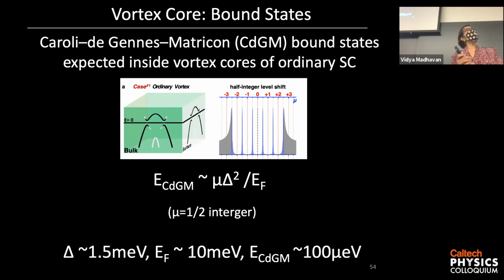So the question is, how do you distinguish these trivial bound states from Majorana bound states? And the first thing is that these trivial bound states are not supposed to occur at zero energy. In fact, the energy of these Caroli-de Gennes states goes as delta squared over E_F, where delta is the gap energy, and E_F is the Fermi energy. So you can calculate this value for this material, iron, selenium, tellurium, and what you find is that the energy of the Caroli-de Gennes states should be about 100 microelectronvolts. So the first Caroli-de Gennes state should be 100 microelectronvolts from the Fermi energy.